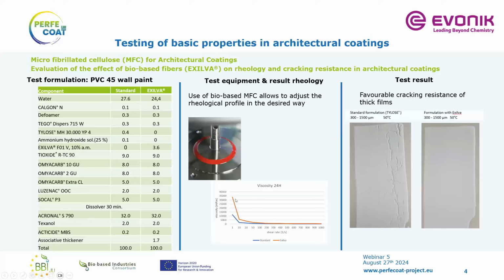On the test equipment, we've looked at the viscosity profile of the paint. We observe that with the Exilva, we obtain a very nice and stable rheology, which provides exactly the right property you need for applying and for the property you need when the paint is on the wall, with this type of profile, as you can see in orange. And this was stable after a week and 2 weeks at 50 degrees. So that's a very good performance.